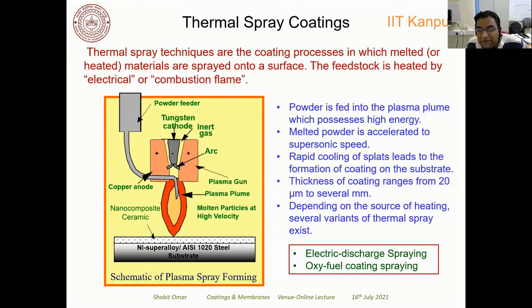So there are various variants of thermal spraying coating, and one of them is electric discharge spraying, and the other is oxy-fuel coating spraying. You cannot make very thin coatings using thermal spraying technique. You can go from 20 micron to several millimeter. Okay, and the melt that is deposited on this substrate is basically called a splat, and they have a certain microstructure, which I will talk about later on.